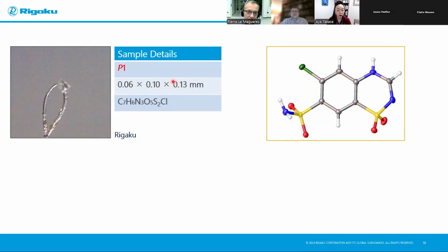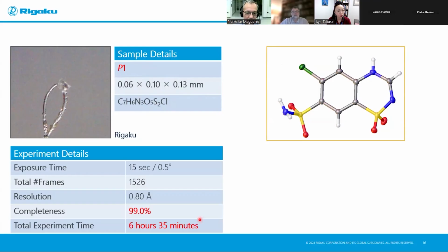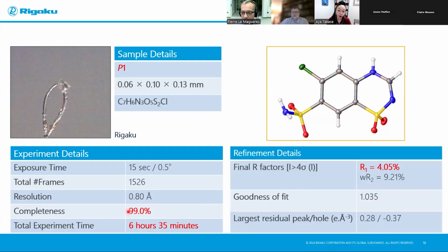I want also to point out the dimensions of the crystal. You see that the thickness of the crystal is only 60 microns, so it's not big at all, and then the other two dimensions are about 100 microns. So that data set was collected in just 6.5 hours. This is the merged completeness, right? This is not the anomalous completeness. The Friedel pairs have been merged here to yield a 99% completeness at 0.8 angstrom resolution. And the structure solution yielded a good R1 factor of basically 4%. So that's the first example, with a P1 crystal.